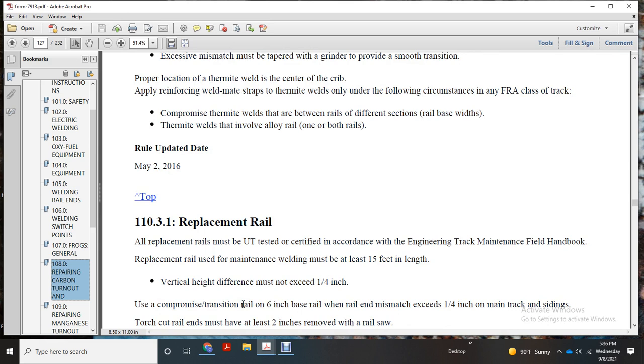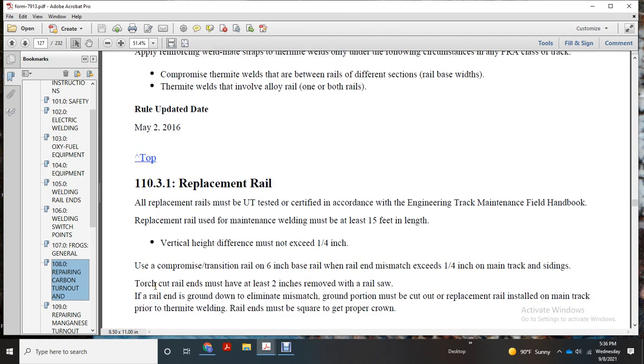Replacement rail. All replacement rails must be UT tested or certified in accordance with the engineering track maintenance field handbook. Replacement rails given the maintenance with welding must not be less than 15 feet in length. Vertical difference must not exceed 1/4 inch. Use compromising transition rail with a 6-inch base rail when rail end mismatch exceeds 1/4 inch on main track and siding. Torch cut rail ends must have at least 2 inches removed with the rail saw, with the rail end ground down. Eliminate mismatched ground portion; they must be cut out with a replacement rail installed in the main track.